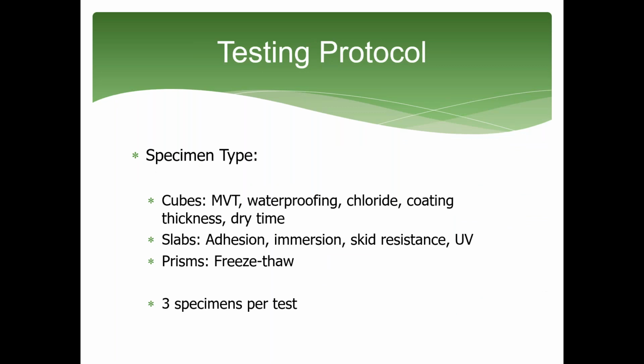There are 3 specimen types: moisture vapor transmission, waterproofing, chloride, coating thickness, and dry time are performed on the 4-inch by 4-inch cubes. Adhesion, immersion, skid resistance, and UV resistance are performed on the 4-inch by 6-inch by 2-inch slabs. And freeze-thaw testing is conducted on the 16-inch by 3-inch by 4-inch prisms. In all cases, there are 3 replicate specimens prepared for each test.